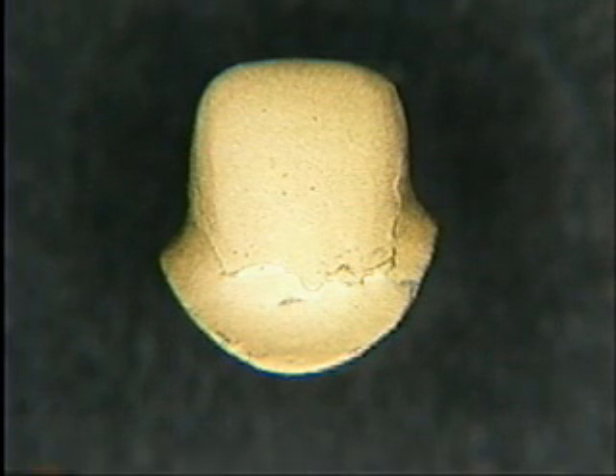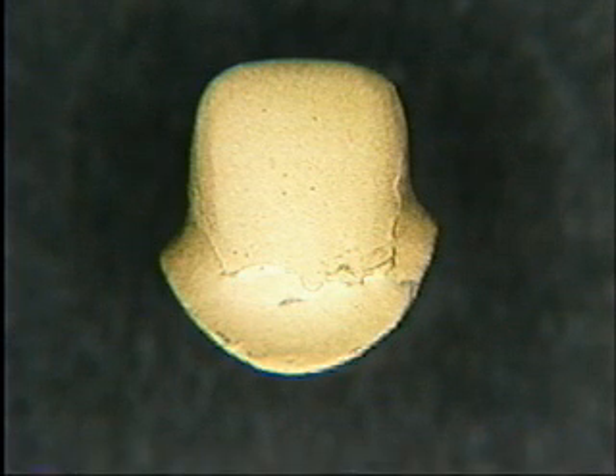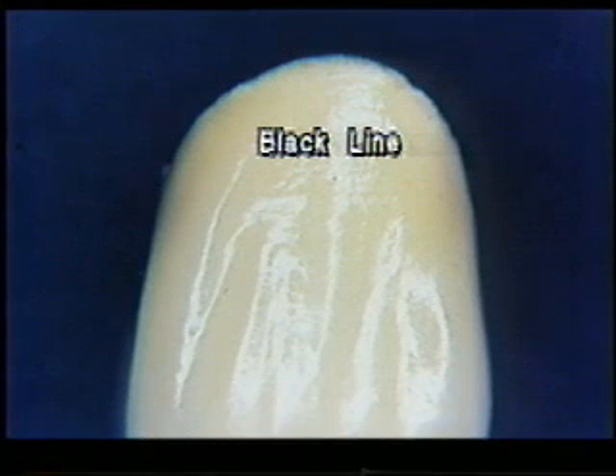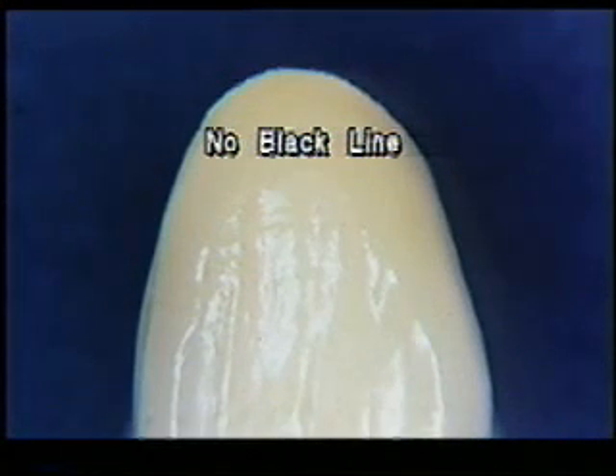But the problem lies in the weak fusing strength between gold paste and alloy or porcelain. Paste opaque of EX-3 can be easily painted right up to the gingival margin and shows very little shrinkage even after baking. No black line appears on the margin. Therefore, even without the application of gold paste, margin color appears bright.